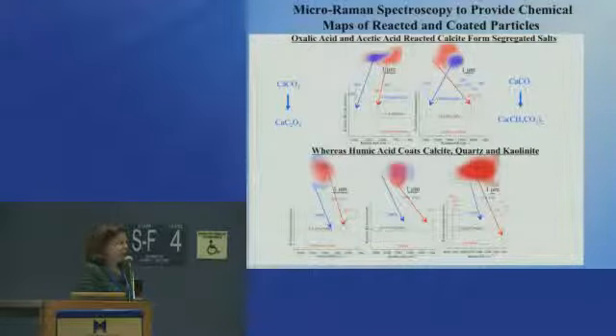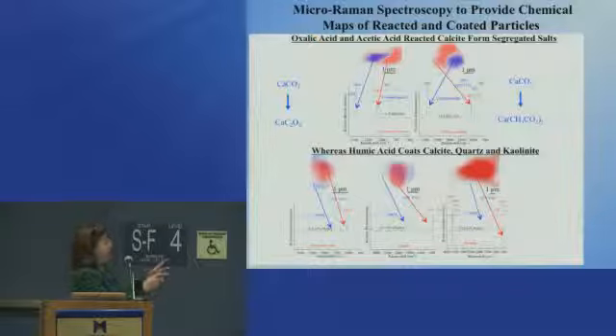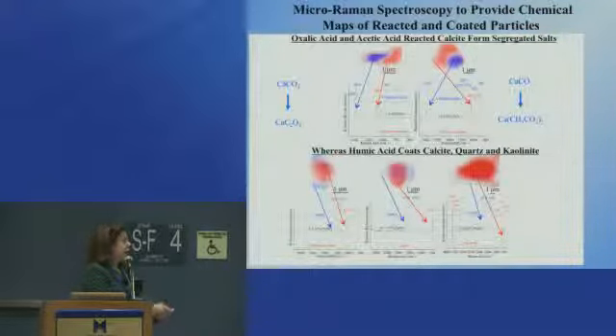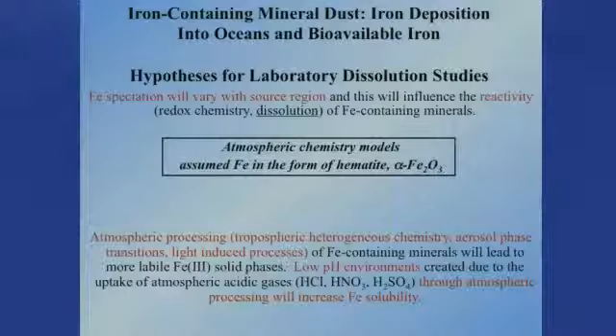Whereas in the case of humic acid, just like that microscopy image showed, we in fact get coatings on calcite, quartz, and kaolinite. So humic acid is a very complex system of many macrocycles stuck together, a large, high molecular weight system that easily coats these particles. And we can see that in our maps. So again, we're starting to get information about composition, but also about some of the impacts of spatial heterogeneity in these reactions. Okay, another example that I want to talk about is the example of iron-containing mineral dust. There's a lot of interest in iron deposition into the oceans and bioavailable iron.